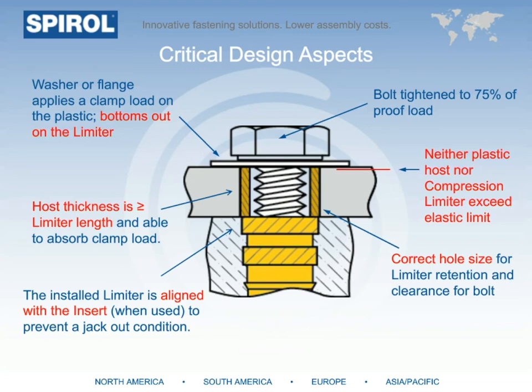If this is not possible, we're happy to offer a recommendation for how to optimize your joint and still achieve that critical metal-on-metal contact. Just like the plastic, we also need to make sure that the bolt does not exceed the elastic limit by assigning a clamp load up to 75% of the proof load. If an insert is used, like in this example, the limiter should be well aligned to prevent a jackout condition. And lastly, the host hole size is critical to ensure the compression limiter can retain its position in the host prior to bolting the assembly.